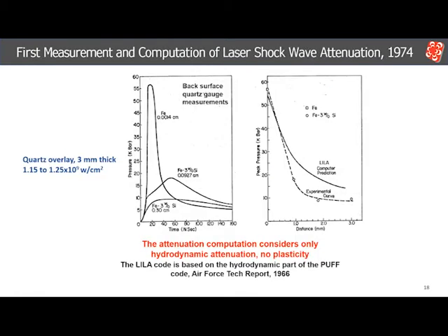These are the first measurements of the decay of a laser-induced shock wave. The measurements were made on the discs of decreasing thickness shown on the previous slide. The back surface pressure measurement was made on an iron film deposited on a quartz disc. LILA was used for the decay computation. It's a hydrodynamic code and shows good agreement near the surface where most of the decay is hydrodynamic. However, deeper into the disc, where plastic work predominates, adding to the rate of decay, the measured pressure decreases more rapidly.